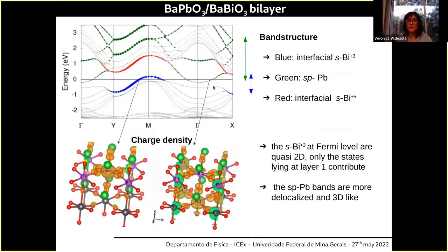And when we look at the band structure of this, and we project in colors the main character, the blue band at the Fermi level has to do with the character of the bismuth 3+ of the interface. And this is the corresponding charge density of this blue band. And this green band corresponds to the wider lead S band that dopes with electrons to the BBO. And this is the charge density of this lead band, which is much more delocalized.